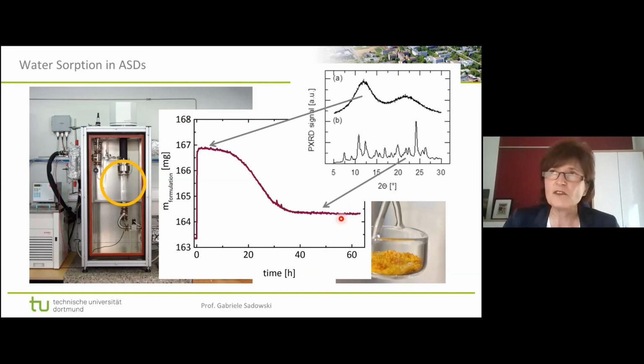In the meantime, we have a much more advanced setup where we can make PXRD measurements in line. So it's not this one, but we have a different apparatus where we can make sorption measurements and at the same time, without taking the sample out, PXRD measurements. So we do have this, but these measurements were done by really taking the sample out and making the measurements. But it's available, of course, combined, but of course, it's much more expensive than the other one.